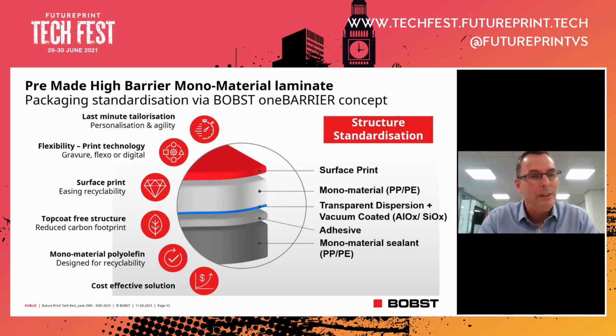The next is the laminate bond strength. And via removing the ink layer from the embedded structure, any limitations related to the laminate bond strength related to the ink are now removed. So we can obtain and achieve higher laminate bond strengths with the removal of the ink layer from the pre-made laminate.